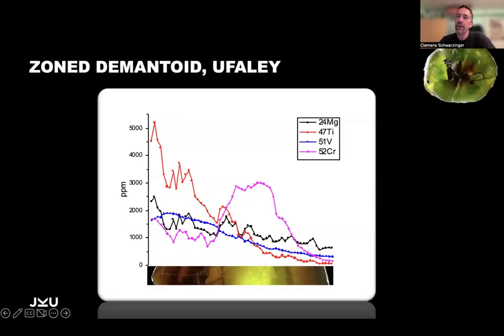Here we have another example of such a crystal. So this is about a 70 carat demantoid nodule. As they're found, it's in the center brownish. Then we have the intense green, and outside a little bit yellowish. And here we have the concentration of various elements versus the position. So we start in the center where we have the brown, and we see that we have high concentrations of titanium. Titanium together with the iron forms an intervalence charge transfer, which is very often in minerals found to be the reason of a brownish color.